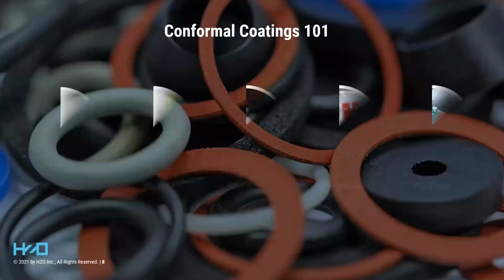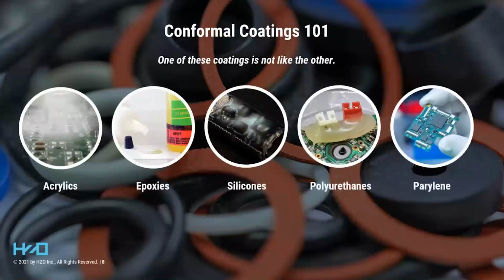To dive a little bit more into the broad families, the traditional conformals are acrylics, which have good electrical properties and are easy to remove with solvents, so they're fairly reworkable. Epoxies, which are typically 2 parts. They're very strong, a little bit difficult to rework, sometimes have thermal mismatch or mechanical mismatch with the substrates, but often add a lot of strength to your board. Silicones, we all know these to have really good chemical resistance. They're preferred for medical applications because they tend to be fairly biocompatible. They can be more expensive though, and they're a little bit more highly engineered than some others.